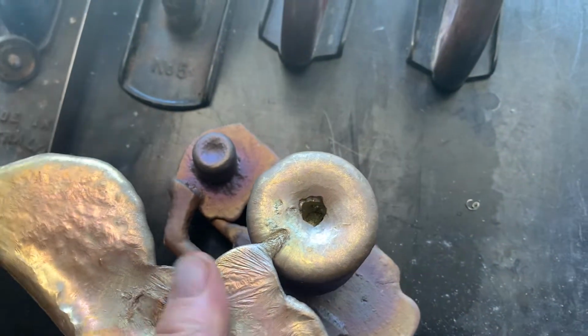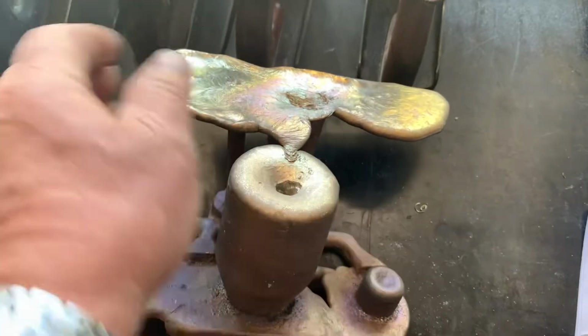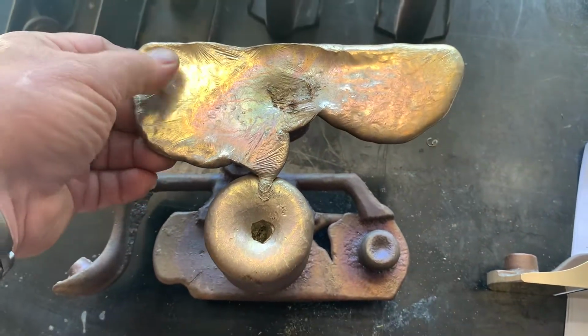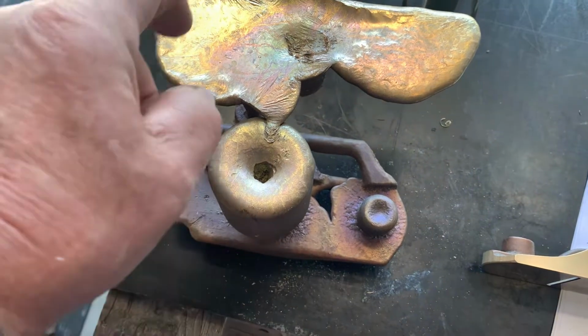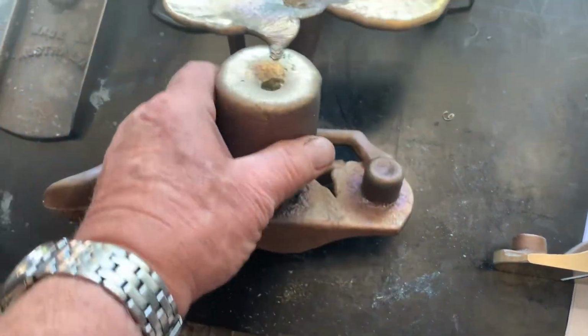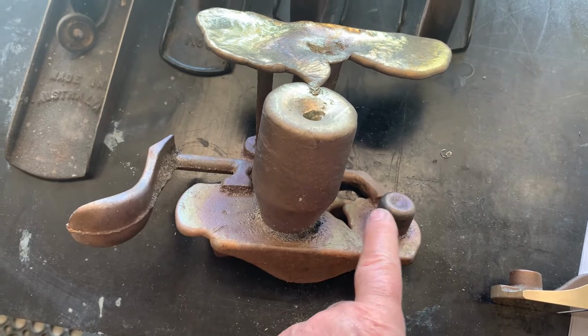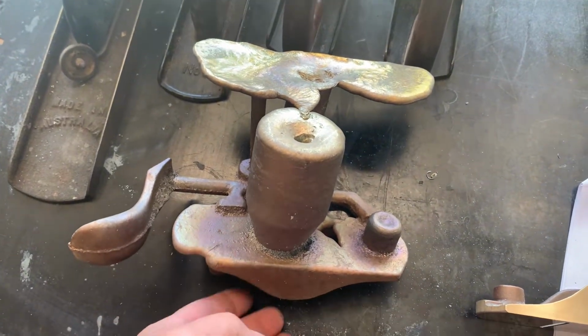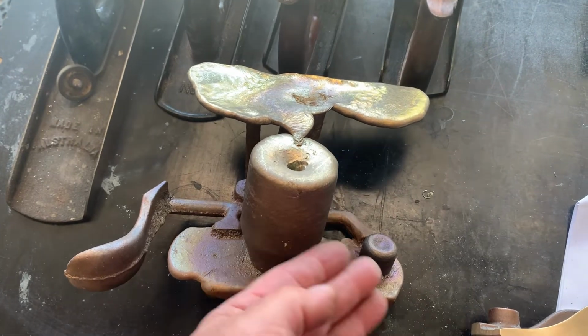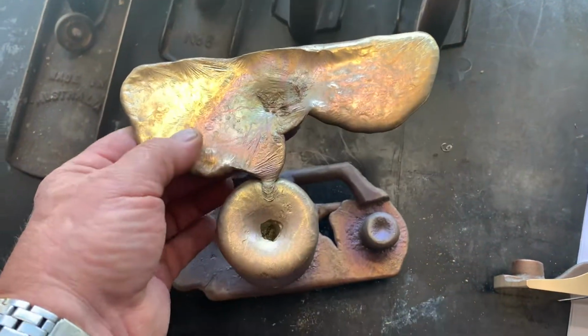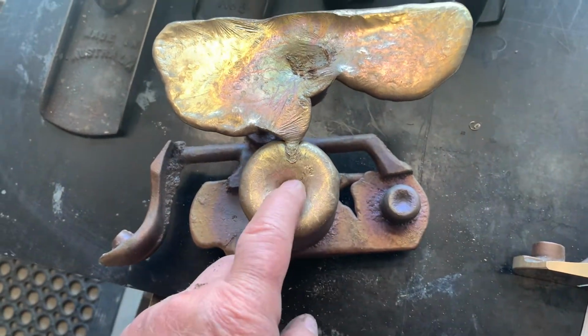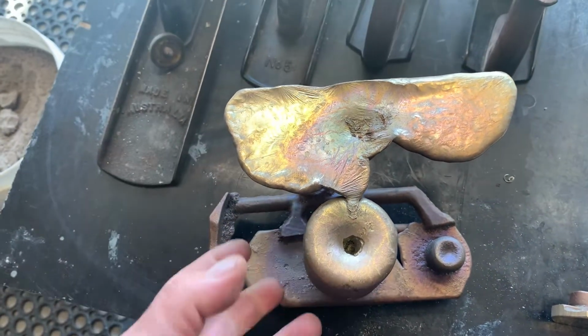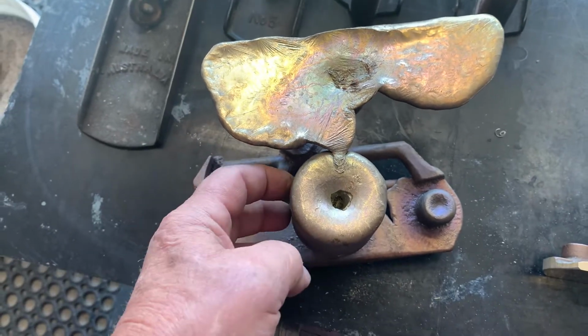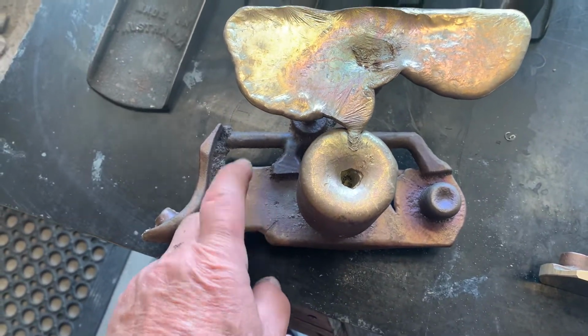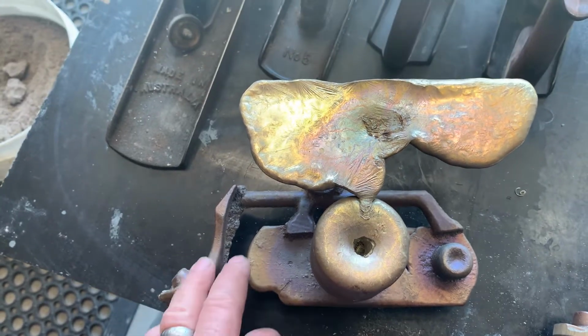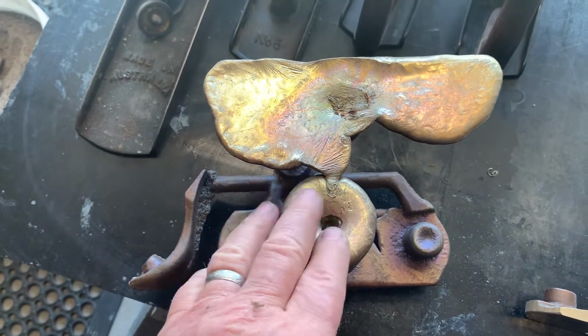So you can see this one here, you can see the beautiful gold. Doesn't it look beautiful? The actual aluminium bronze looks absolutely beautiful. And you can see these top bits here, and these are what we call risers. The idea of the risers is that the metal fills the mold up and then comes up here, and you can see they're dimpled, and that's the shrinkage. The idea of putting the risers in is that this will shrink, and your actual job won't shrink. You don't want it to shrink. It'll probably shrink a little bit, but not a great deal, and so all the shrinkage goes out of there.